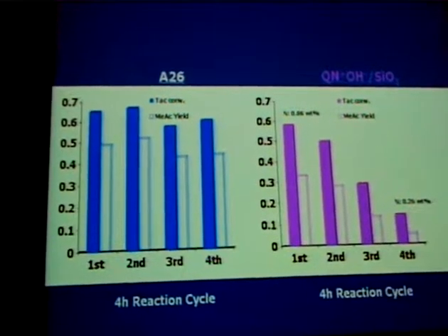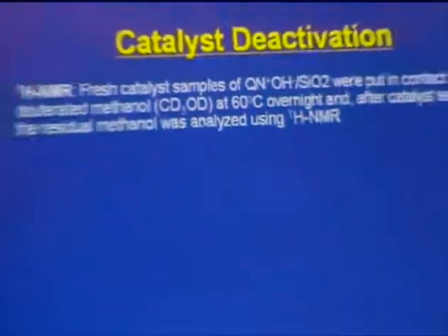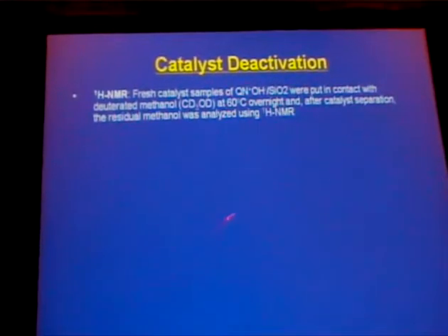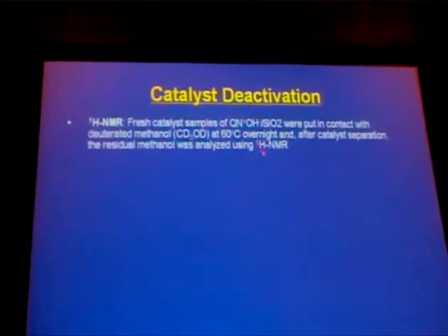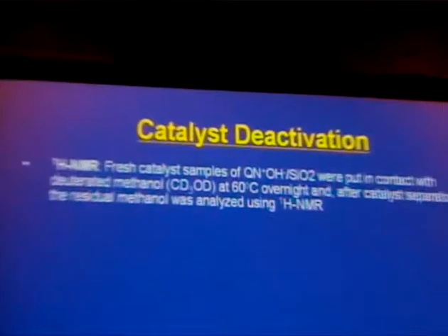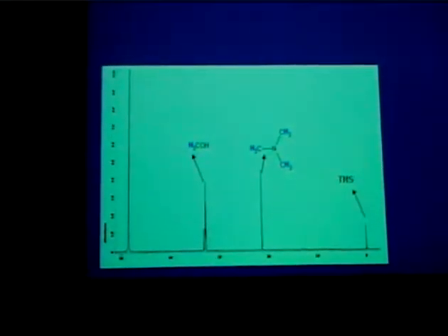In order to understand what is going on with these catalysts in terms of deactivation, we did some NMR experiments in which we put the resin and we put the silica catalyst in contact with the alcohol, methanol, overnight. And then basically what we did is we took NMR just to see what organic species were leaching from this catalyst. What we found is that the silica catalyst is leaching this amine, trimethylamine.